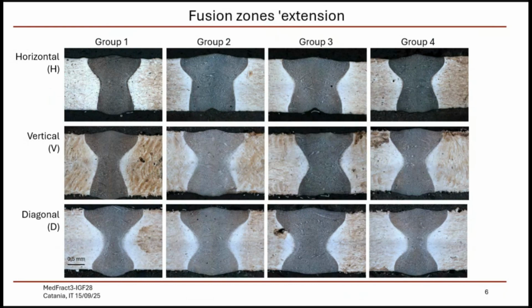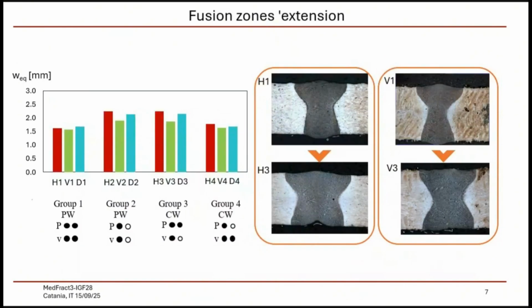Here we are comparing the fusion zone extension because often this is an indicator that is used to make comparisons between joints. So if we transform this matrix into a bar plot, we can see if there are some trends that relate the fusion zone extension to the parameters that were adopted. And here you can see there is a trend related to the process parameters, but specifically to the welding speed. Actually, laser power and power modulation don't give a great contribution, not as much as the welding speed. And as you see, the lower the welding speed, the larger the fusion zone extension.